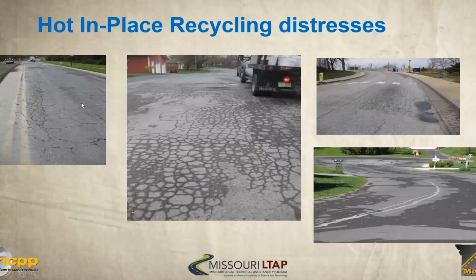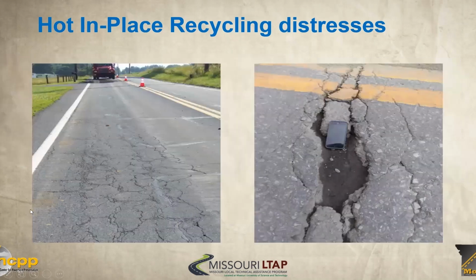So what kinds of distresses can hot in place address? Well, here's a few slides actually, and it's important to make a distinction of what's causing these cracks. So coring is recommended in any of these in-place recycling techniques. We want to make sure that this isn't base related, that this is more of a surface asphalt situation. Here's a picture of a phone over a crack. And then here's another issue here with the pavement. This could be a widened road, it kind of looks like, as you have this outside, kind of in between a wheel pass all the way out to the edge of pavement.